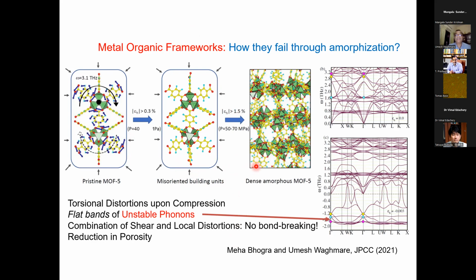So what we did is, again, the theory which we applied to crystal transition. We look at the phonon dispersion of MOF5, and you see it's a beautifully stable structure. There are no unstable phonons. But as soon as you compress it by even 0.3%, this is hydrostatic strain, you will see many phonons become unstable here, as shown in this part. These are below zero. And these unstable phonons form flat bands.